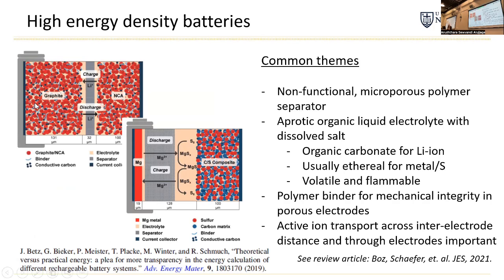And because I promised talking about polymers, I'll just point out a couple common themes between these two systems, our commercial system and a potential next generation system. How we currently make these is with non-functional, but porous, inert separators, right? So in the commercial cell, we have microporous polymer film. It's usually polyethylene or polypropylene or tri-layer laminates of those coated in metal oxide particles that are used to just separate the electrodes.